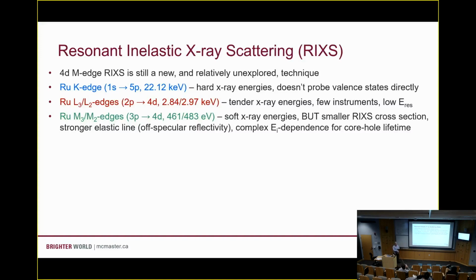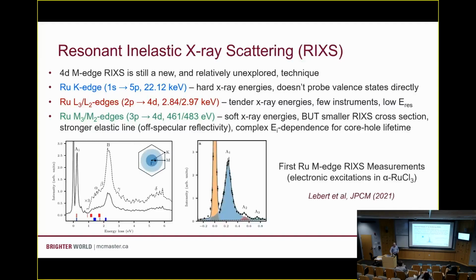And the L edge RIXS has a high resonant enhancement and a big scattering cross-section. Okay? K edge up here is not as great because you're not directly probing the valence levels for these transition metals. Okay? M edge also gets you the valence levels, but has a much smaller cross-section. Okay? And so the counting times become very, very long. You have to worry about trying to see these little inelastic features compared to a stronger elastic signal, and the energy dependence can be a little more complicated. The advantage you get is when you move down to these smaller incident energies, the energy resolution does become better. Okay, so it's a little bit of a trade-off, but these are measurements that are now possible.